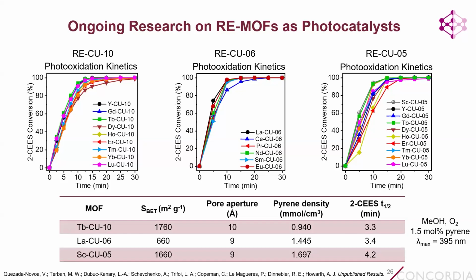Okay, so now we can actually look at the photooxidation behavior. So now that we know the structure of these 3 MOFs, we can look at how they perform for the photocatalytic detoxification of the sulfur mustard simulant, and then try to understand how structure relates to function in these catalysts. And so these are just the kinetics, the conversion versus time for the 3 different series of MOFs. And here at the bottom, I've summarized the fastest MOF catalyst from each of the 3 series.